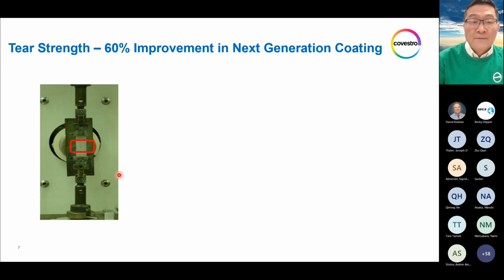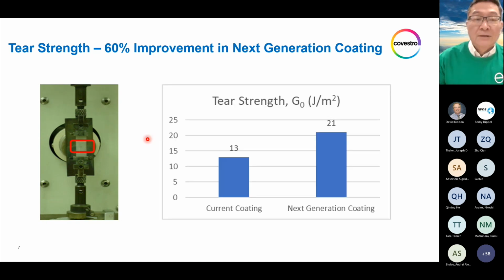You load a cured primary coating film. Then next, we make a well-designed cut according to the ASTM method of tear strength in the middle of the cured film. Then we pull the cured film apart to measure the force at the time when the film breaks, when this crack propagates to the breaking point. The force is recorded and tear strength is calculated in terms of a term called G0.